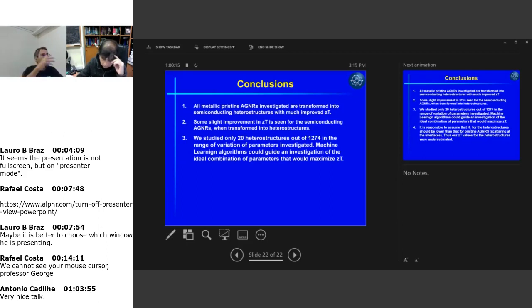And we didn't do all the variations in n, lowercase n and lowercase m that we could. So if we did all the variations possible, we would have 1,274 different heterostructures. So it's very possible, as I showed you, there was an increase of 4 orders of magnitude in ZT. It's very likely, it's very possible that one of the changes in parameters there would give you a much improved ZT.